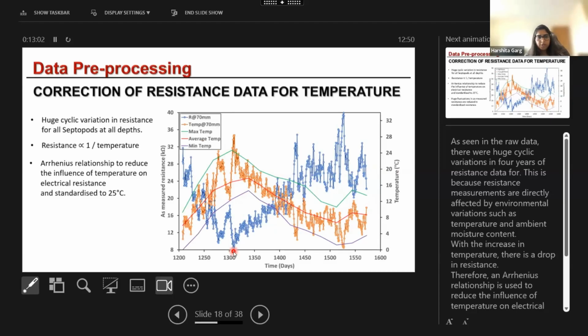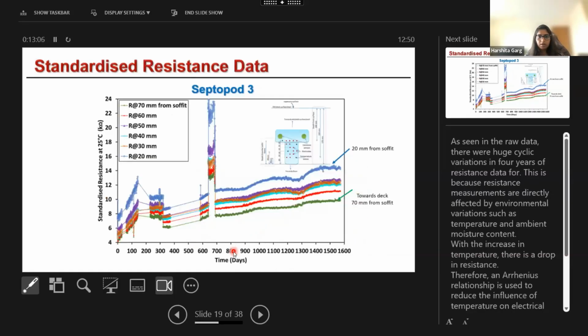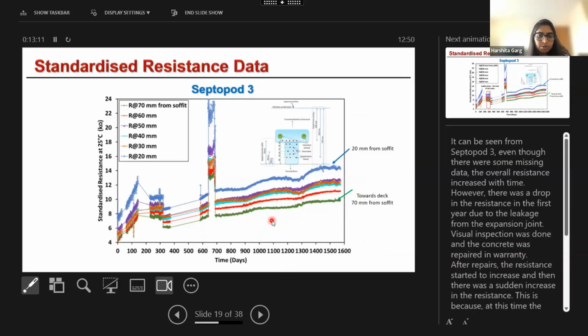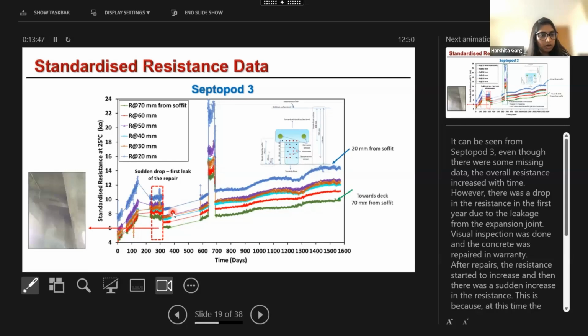Now the huge variations that we saw in the previous slide are reduced. Here it can be seen in Septopod 3, those huge variations are now showing that the resistance is overall increasing rather than such varied sensor data. Even though the resistance data is increasing, there is some variation. Resistance was increasing, and then suddenly there was a drop. This drop was identified from the sensor data, and on visual inspection, it was identified that there was leakage in the newly repaired concrete near the expansion joint. The repair was done soon after identification, and after that, we can see the resistance started to increase again. Even though there is some missing information, resistance was overall increasing.